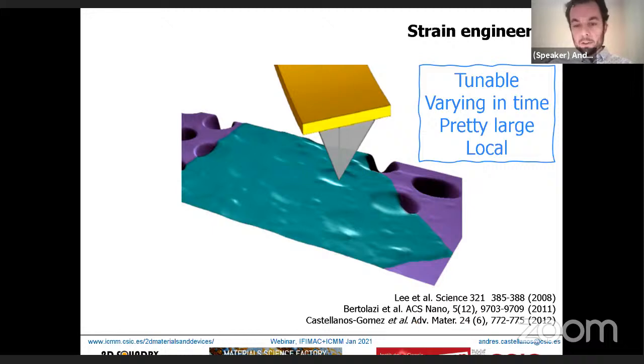From indentation experiments, for instance in molybdenum disulfide, they have seen that these materials can stand quite large deformations, around 10%, which is very close to the fundamental limit where breakdown occurs because the bonds break. The force becomes so large that the bonds tend to break instead of the defects coalescing and starting cracking.